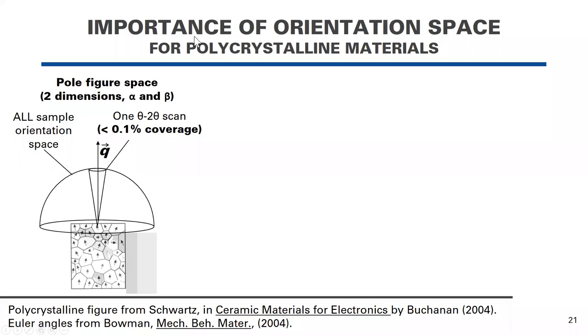I want to emphasize the importance of orientation space, in particular for polycrystalline materials. If you just do the types of measurements that we've looked at so far, you're only sampling one scattering vector in your sample. But this talk is dedicated to polycrystalline materials of all types, where we want to measure the scattering vector in all orientations of the sample.